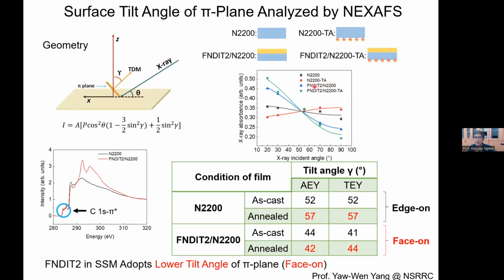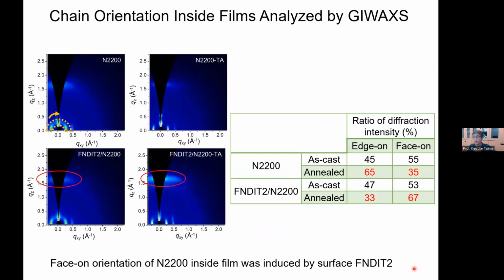But if you have this fluorine-alkylated NDI on the surface, you can see that the dependency is negative. So with a larger incident angle, you get a smaller absorbance of the X-ray, and the thermal annealing further enhances this anisotropy. You can use this equation to get the average tilt angle of the pi plane, and you can tell that without anything on the surface, it's edge-on, not very vertical, but still the angle is 57 degrees. With this fluorinated chain, it's 42 degrees. These are close to face-on. So it means that this monolayer on the surface shows the face-on orientation. But does it affect the inside structure?